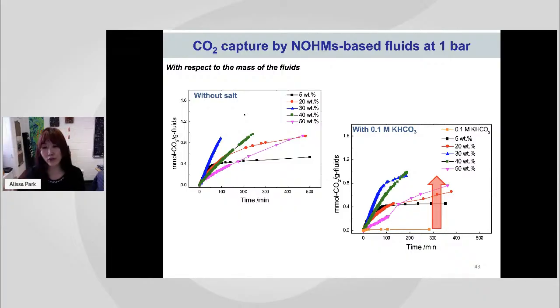As soon as we introduce our NOHMs into the system, we have orders of magnitude increase in CO2 loading in this electrolyte. So by doing so, we were able to hopefully, once the catalyst is very good at per pass conversion, now we should be able to host both capture and conversion reaction in a single fluid unit, and this will really improve the overall sustainability and energetics of this tandem reaction.